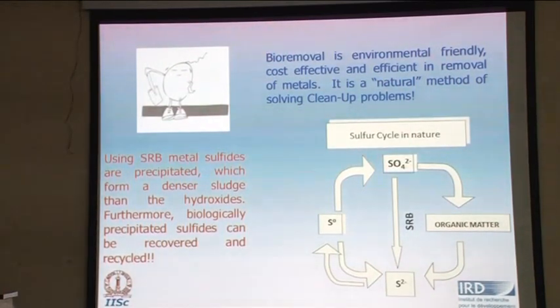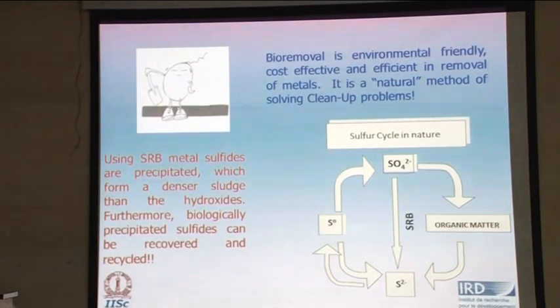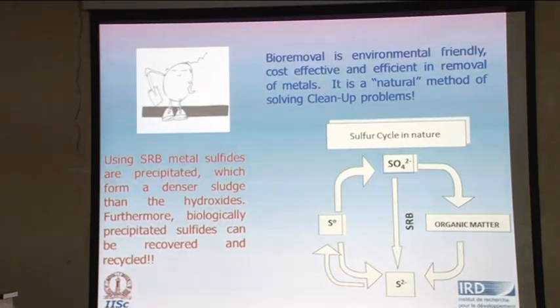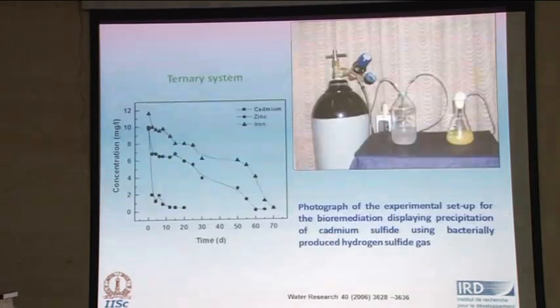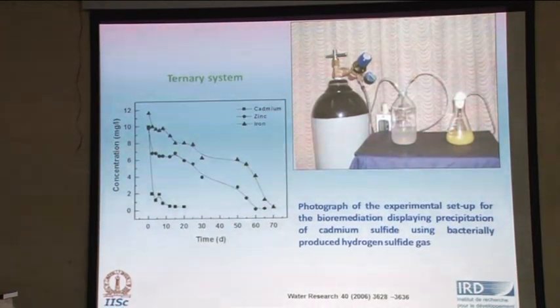So various organic electron donors have to be used, and the sulfate reducing bacteria uses either lactate or acetate. And what we have done is we have developed a strategy wherein we produce the hydrogen sulfide. The sulfate reducing bacteria basically releases hydrogen sulfide by this metabolic process, and that hydrogen sulfide, which is biogenically produced, is used for the precipitation, in this case of cadmium sulfide. So what you see here is the cadmium sulfide precipitate, and interestingly, when you look at different elements, when you have multi-element solutions like cadmium, zinc, iron in this case, you can see that the solubility product principle with respect to the sulfides is very clearly obeyed.